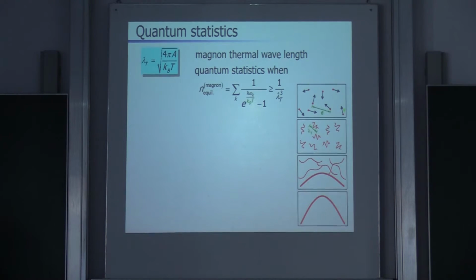So at equilibrium, we know that we have a distribution function which looks like that, and this is the magnon number. Now, we also know that this is a really quantum distribution function if the de Broglie thermal length is larger than the inter-magnon distance, right? So if this one here is larger than this parameter here, we know that the magnons overlap and we can expect quantum effects.